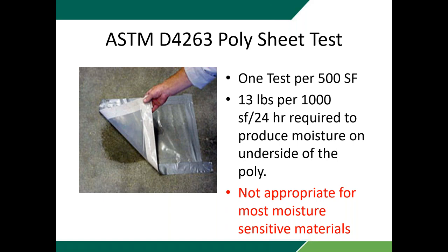So in this particular test, they take a given size of poly or visqueen, they prepare the floor, and then they tape this down to the surface for a given period of time. Then they come back and pull the visqueen and look for evidence of moisture on the underside of the visqueen, whether that be in the form of droplets or dampness in the concrete. If you see that, it's indicating there's moisture. Usually they run about one test per 500 square foot if they're following the ASTM designations.